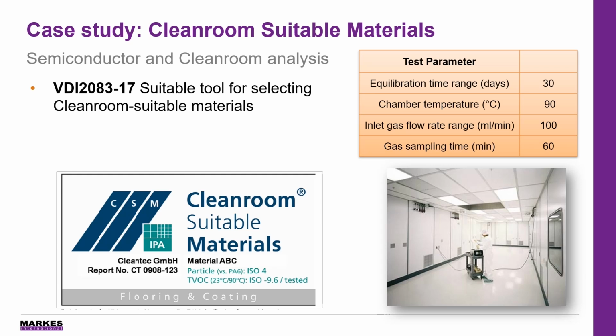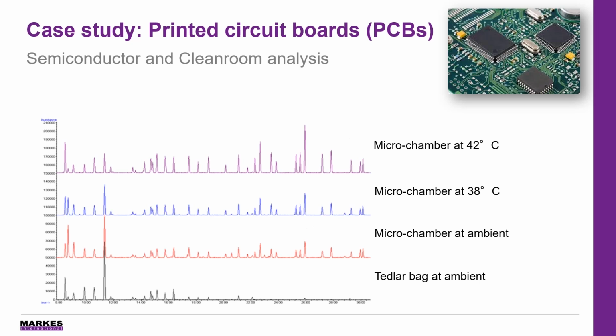In addition to testing the materials used for the clean rooms, we also need to have a look at product emissions for quality control. So here what we have is some traces of a printed circuit board analysis. So the traditional methodology for looking at printed circuit boards is using a Tedlar bag. Now a Tedlar bag is like a large non-emitting plastic bag which a piece of material can be placed inside. And a flow of gas is applied and a headspace is created, and then that's drawn onto a sorbent tube. Now in this application it was typically run at ambient. And the problem is that a lot of the compounds of interest are the more semi-volatile compounds. And they tend to get stuck to the inside of these Tedlar bags.